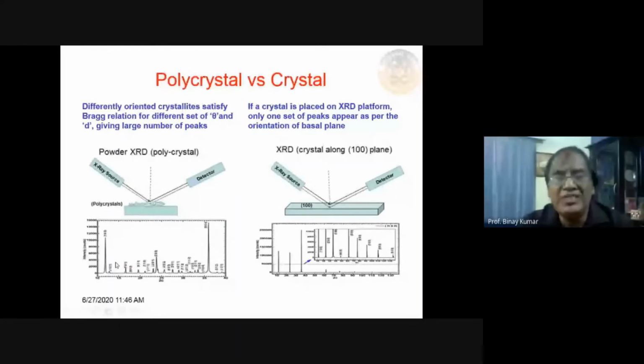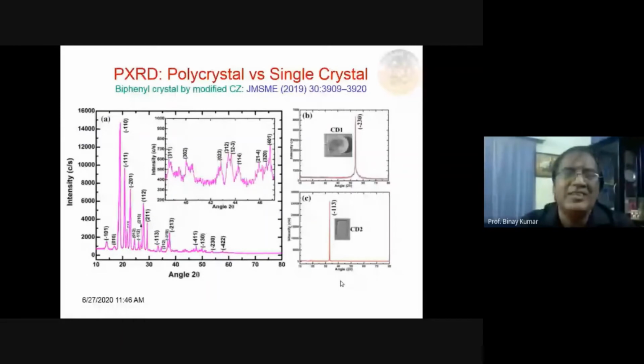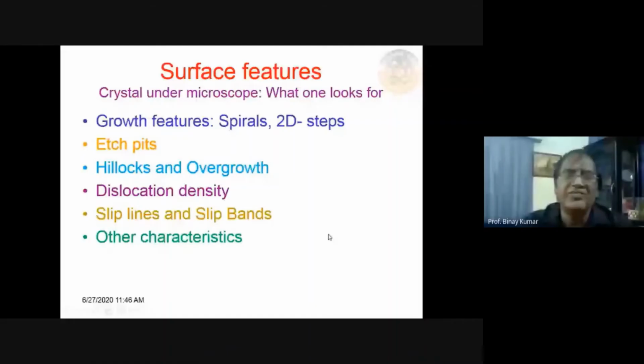But if I put a single crystal in the same powder XRD system with one flat plane, say it is 100, then what will we get? We will get 1, 2, 3 lines, which all belong to the same family, 100, 200, and so on. This is experimental evidence: in the case of a biphenyl crystal, in powder form we have so many peaks, but if we cut the crystal in two specific directions, you get two different single peaks corresponding to this. Now it is a surface feature.